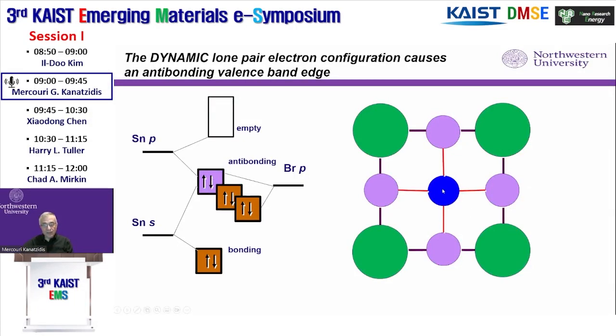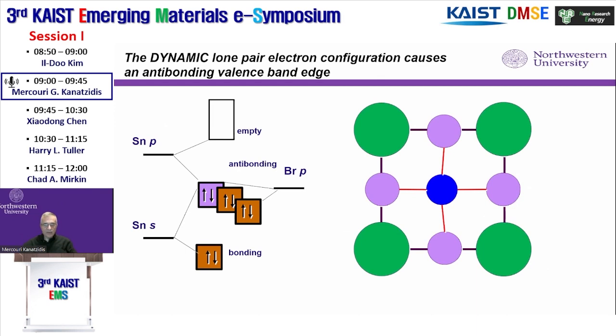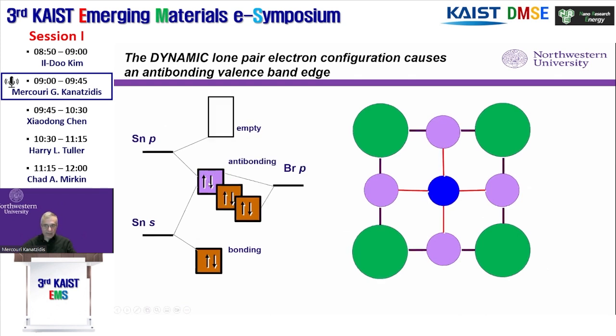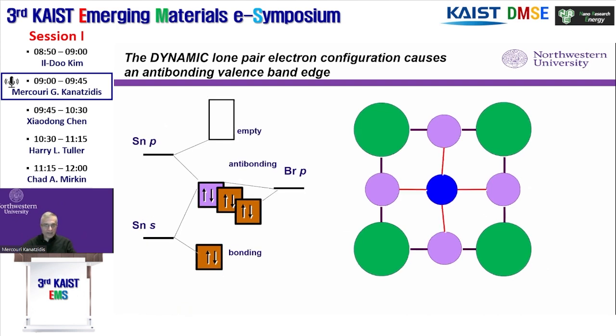So if you imagine an energy diagram where you have the blue atom, which is the lead 2+ or the tin 2+, in the center of the octahedron, the highest occupied molecular orbital is s2 in character. So it has lone pair character, and that's the highest occupied orbital. And by extension, the top of the valence band has lone pair character. Now, when you start moving this away from the center, you stabilize the lone pair as it gets stereochemically expressed. And as you stabilize the lone pair, you stabilize the top of the highest occupied state, and it comes down in energy. And so when you go off-center, and it's a dynamic process, it doesn't settle. That causes part of the dynamics and the disorder in this material.